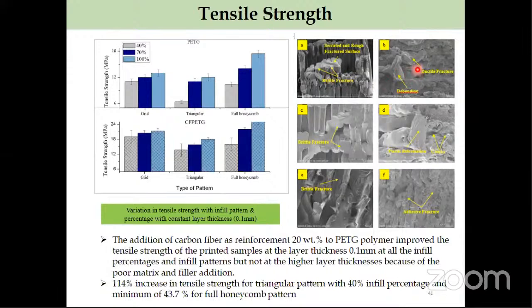Say, for example, in case of the non-reinforced, we could see brittle fracture, while in these images, the fracture was ductile, and the carbon reinforcement, at lower layer thicknesses actually helped in improving the interbonding strength. But at the higher layer thicknesses, because of poor matrix and filler addition, the trend was reversed.